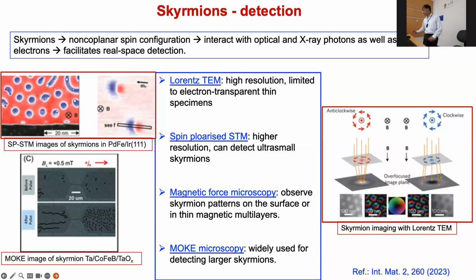Now, these are complex spin textures. How do you detect them? The conventional go-to method in quantum magnetism is neutron scattering, but neutron scattering gives you long-range magnetic ordering. Here we are talking about short range, at nanometer level resolution in real space. Fortunately, because of the non-coplanar spin configuration, they interact with optical and X-ray photons as well as electrons, which can be used to develop methods to detect real space spin configurations at a nanometer resolution.